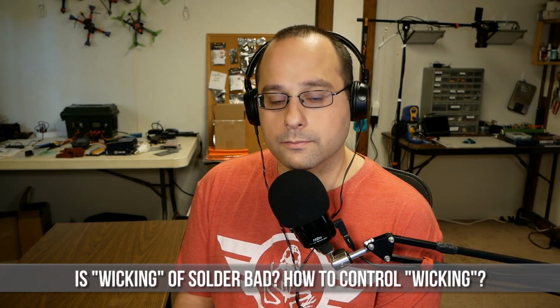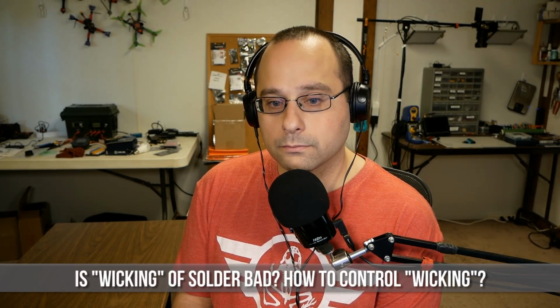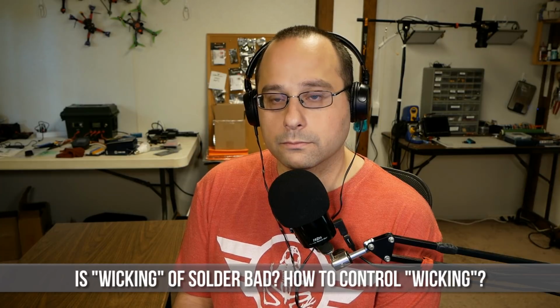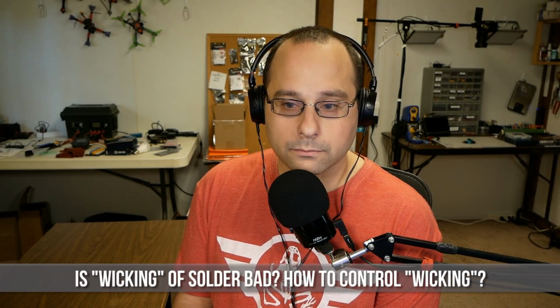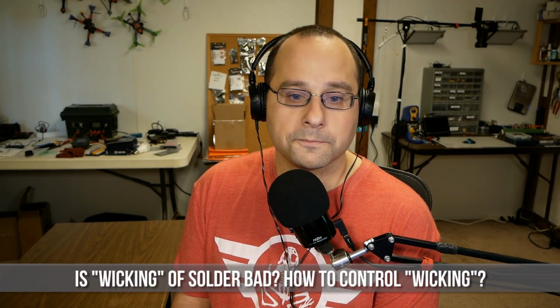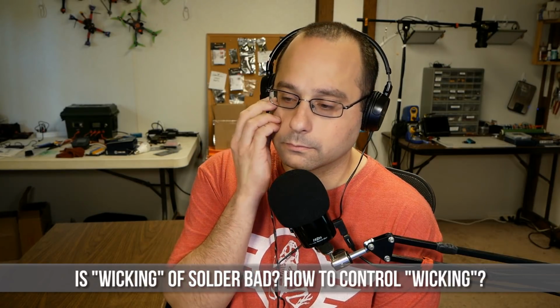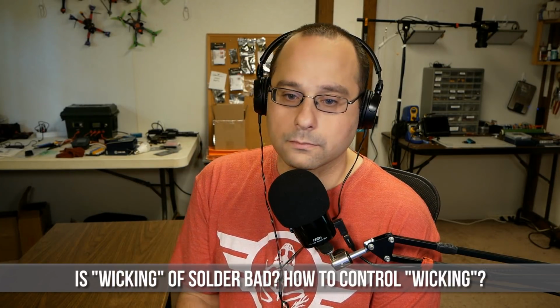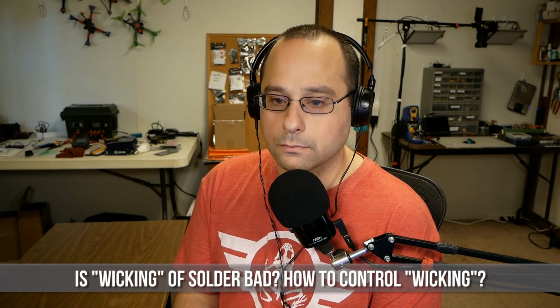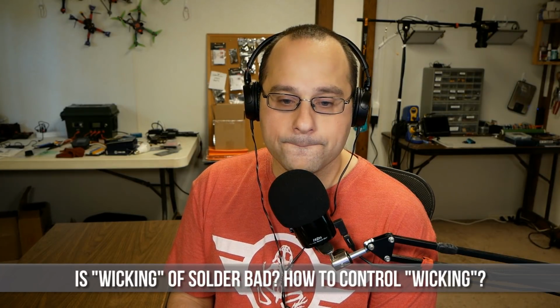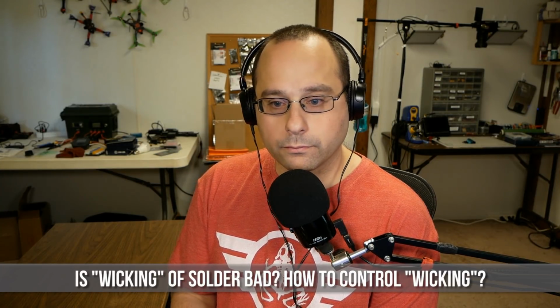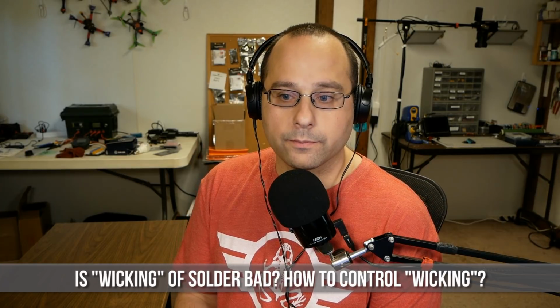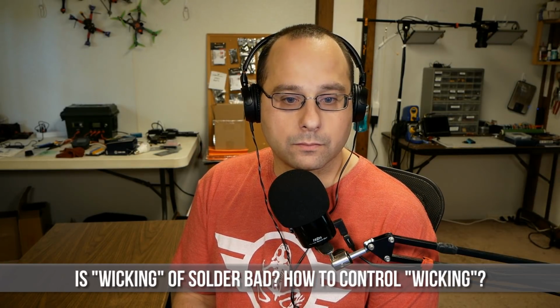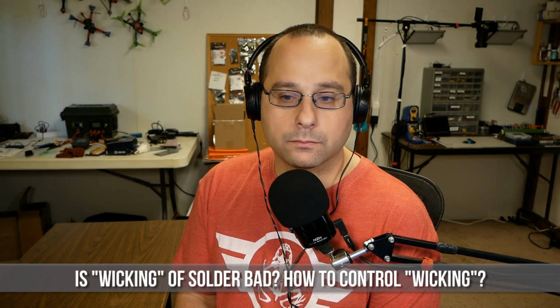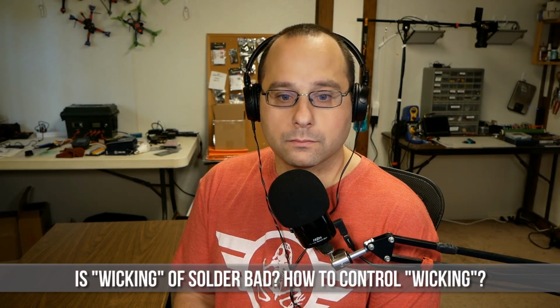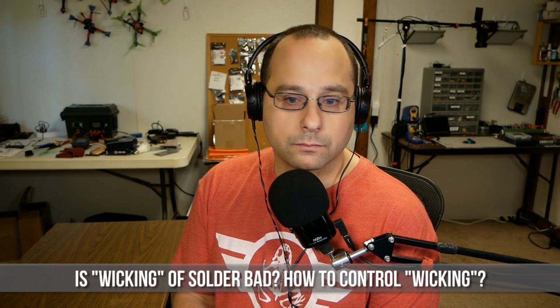Right. The other advantage of the lead-free is it is stronger than a tin-lead, because it's got some silver in it, say 3.5% silver. It makes it stronger, but it melts at a much higher temperature. It's a lot more expensive. So yeah, if you have some lying around, you could use it, but you really don't need to go out and buy it, just because of the excess cost. It's usually at least twice the cost of a 63-37 or a 60-40 solder.